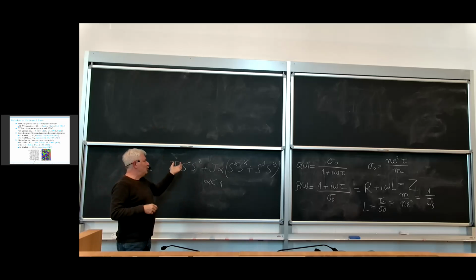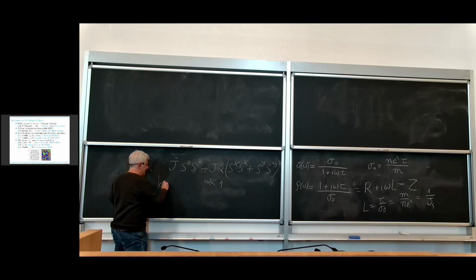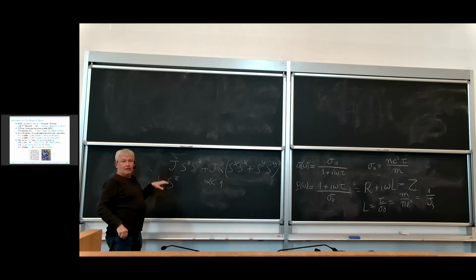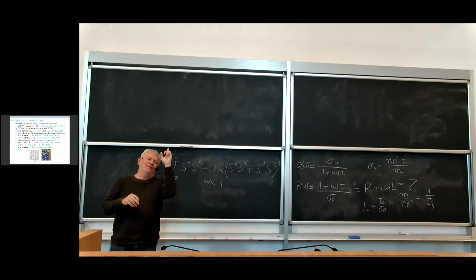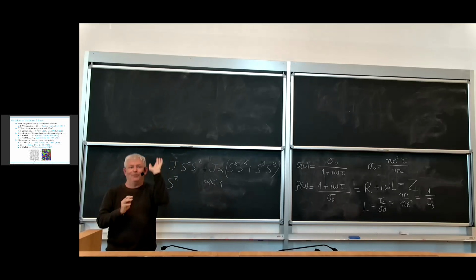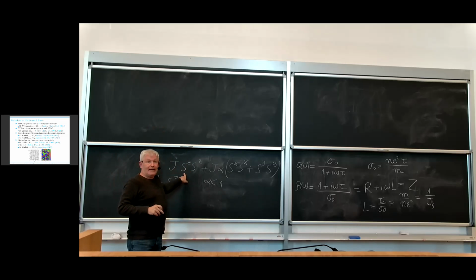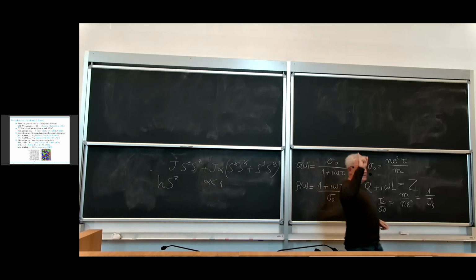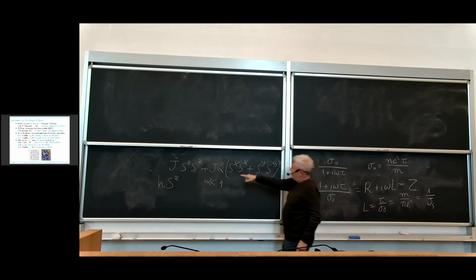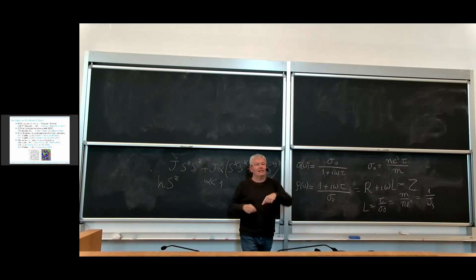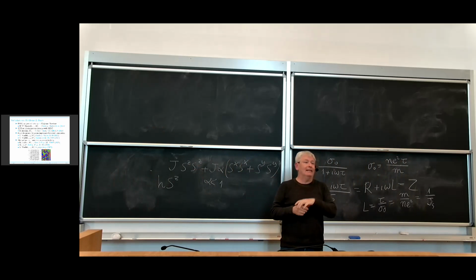Now, if you put some disorder in the form, for instance, of a random magnetic field coupled to SZ, you can create regions where locally there is an average field pointing up. So you favor the ground state where the spin is pointing up, and other regions where you favor the ground state with the spin aligned along Z in the negative direction. And this is just the effect of disorder.